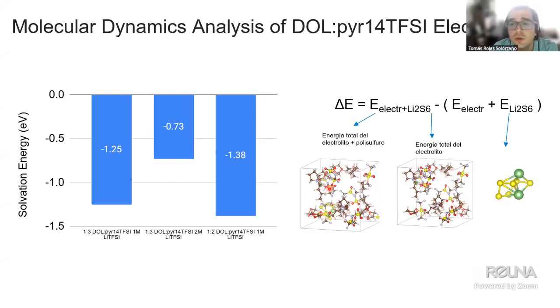But it's important to know the solubility of these polysulfides in the electrolytes. And moreover, how that solubility gets affected by the presence of the ionic liquid. So we modeled 3 different sizes with 3 different concentrations, and we modeled the system as a whole completely, then the system without the polysulfide, and then just the polysulfide. We calculate that difference in energies, and that gives us just the energy of the solvation of the structure, meaning how strongly the polysulfide interacts with the rest of the electrolyte. And we obtain these values here. This is the concentration of ionic liquid with the DOL, which is another typical organic compound used in these electrolytes.